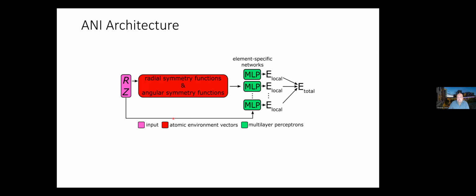And therefore, the approach is very simplistic. You have purely geometrical descriptors. You featurize, compute the symmetry functions, what we call radial and angular symmetry functions, pass them into a very simple neural network, a multi-layer perceptron, compute this fictitious local energy, sum them up, and get the total energy. And so this is how to train, how to do simulation.